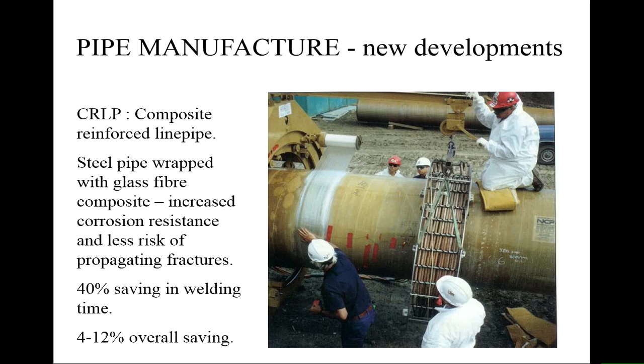So effectively you can see the process here. The steel is wrapped with glass fibre composite, and you're almost using the composite as your corrosion protection layer as well, because you don't have to paint these in quite the same way. And this is particularly good if you want to reduce the risk of long propagating fractures, because you've got almost like a compressive winding around the outside. I'm told, and I can't say anything other than what I was told, that it saves in welding time and it can save in costs overall for these very large diameter pipes.